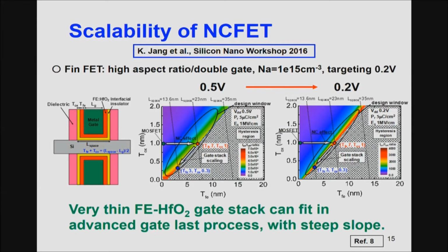The next interest is the scalability of this material. I was wondering if this kind of negative capacitance gate stack can fit into advanced CMOS technology. It's a gate-last process, and it has a very narrow trench after pulling the dummy gate. I was wondering if it can fit into this technology. This graph again shows the I-on/I-off contour plot as a function of ferroelectric thickness and interfacial layer thickness. And again, luckily at 0.2 volt, there is a process design window. So this system can fit into the gate-last process in the 10 to 20 nanometer gate range. This is also good.